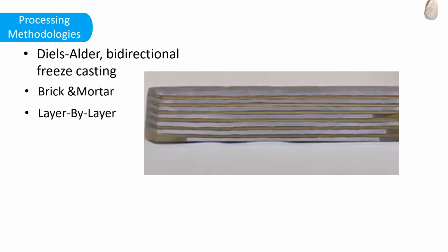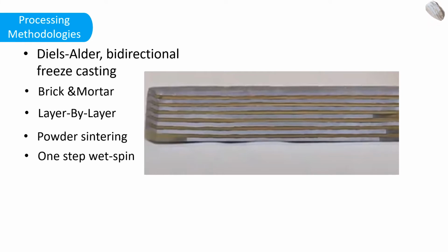Layer by layer arrangement is another method, where the rigid part and soft part are arranged layer by layer to obtain a 3D bulk structure. Powder sintering is another method where metal alloys can be powder sintered to obtain a nacre-like structure, which has been successfully created to form implants. One-step wet spinning is another method where 1D fibers can be created, where graphene oxide fibers have been wet spun in order to obtain a nacre-like structure.